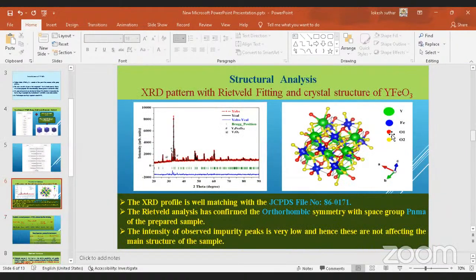Now this is the result and discussion part. Now this is structural analysis. The first figure is showing the room temperature X-ray diffraction pattern with Rietveld fitting. It is clear from this figure that there is no major impurity peak observed, which proves that the material has been successfully synthesized in the desired phase. Also, this XRD profile is well matching with the JCPDS file number, and the Rietveld analysis has confirmed the orthorhombic symmetry with the space group Pnma, and the intensity of the impurity peak is very low, which proves that these impurity peaks are not affecting the overall structure of the synthesized material.